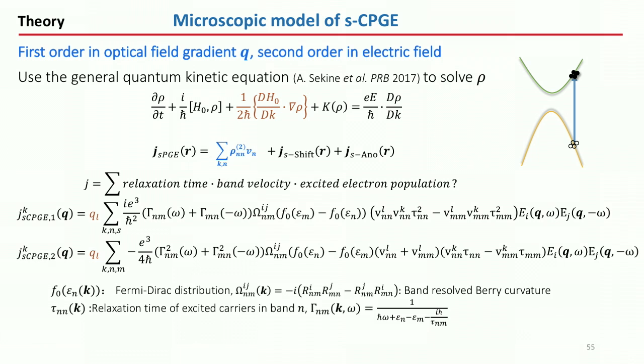They are proportional to the square of the band velocities, and this becomes important. And they also carry what is called information of the Berry phase, Berry curvature, indirectly related to Berry phase of the system. So it has all these unique attributes.